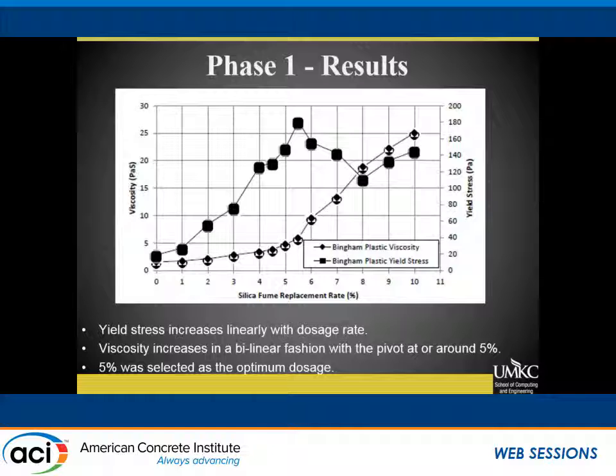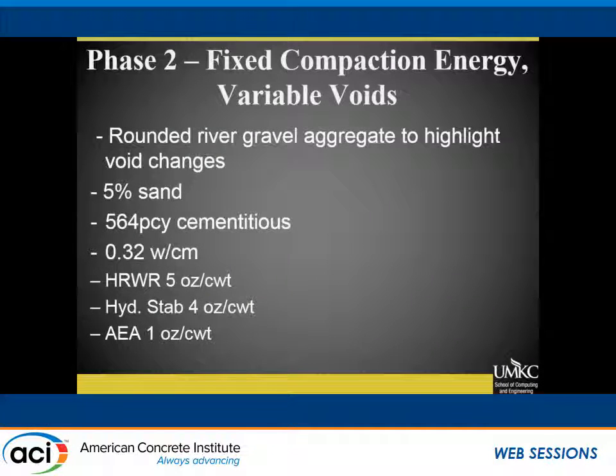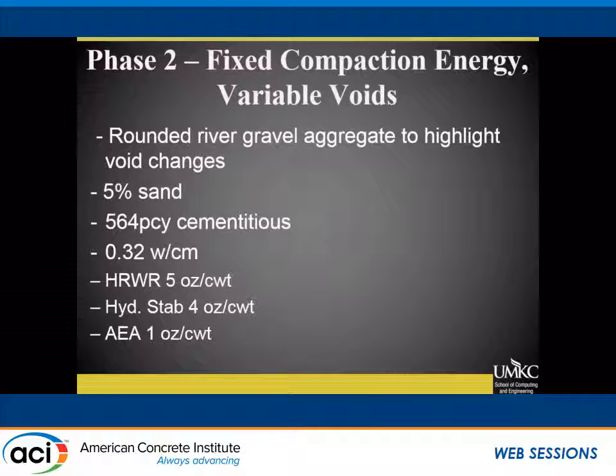Let's run with 5%. So second phase, we're going to use rounded river gravel. We're going to highlight changes to void content. We're going to have fixed compaction energy and kind of standard Pervious mix design. A little bit of sand in there, hydration stabilizer, water reducer, air entrainment.